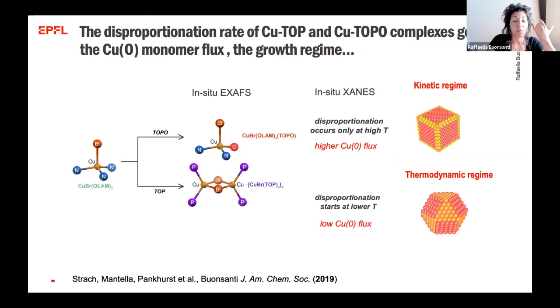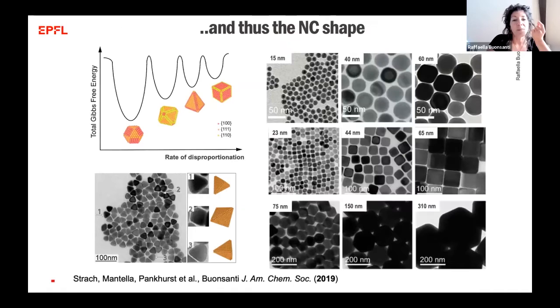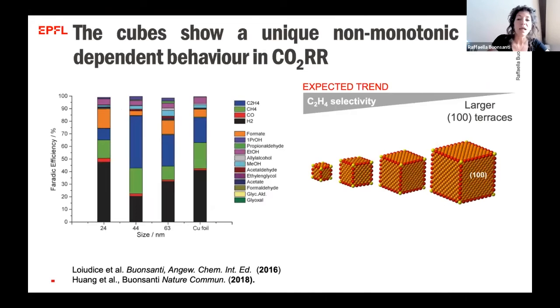Now, having learned that what matters here is the disproportionation rate of these complexes, we were able to control the rate of disproportionation and play with the injection modality and the injection temperature, injecting the pre-synthesized complexes. And we were able to synthesize spheres of different sizes, cubes of different sizes, octahedra of different sizes, and also to access tetrahedra that had not been synthesized up to now. We were now ready to test these nanocubes for CO2 reduction and to learn about their behavior.